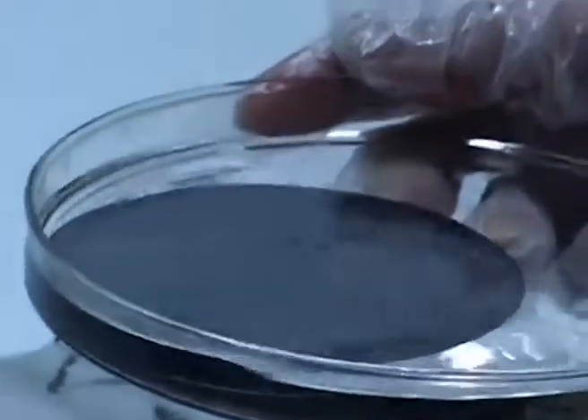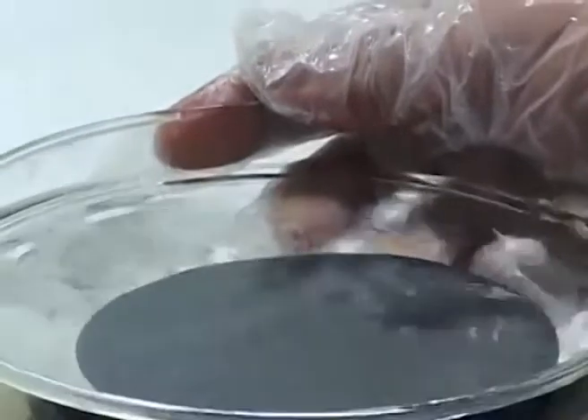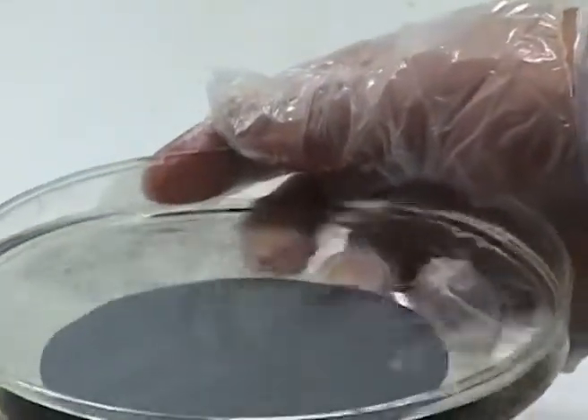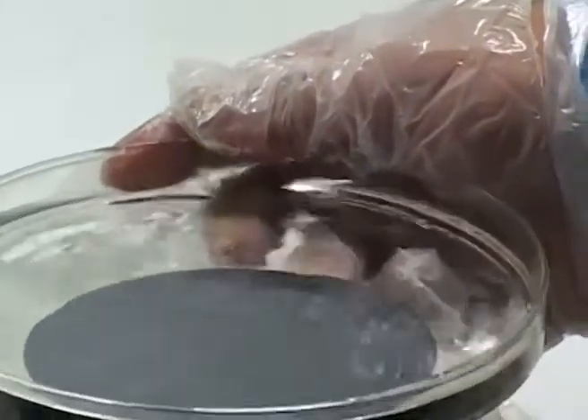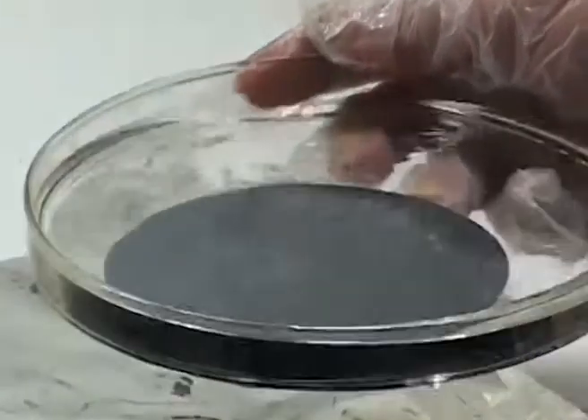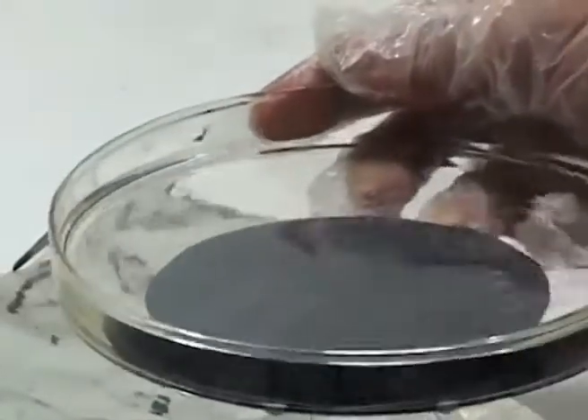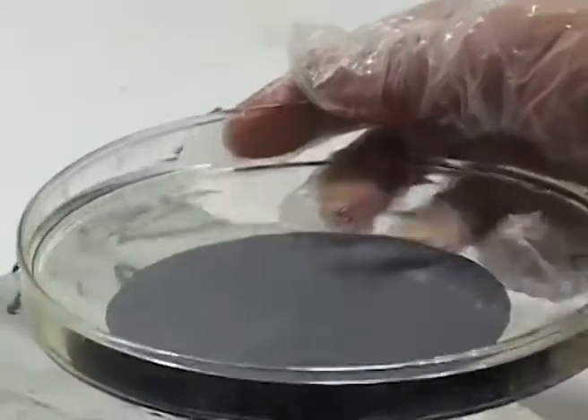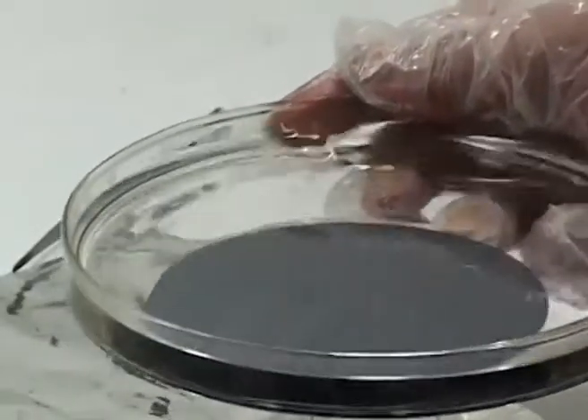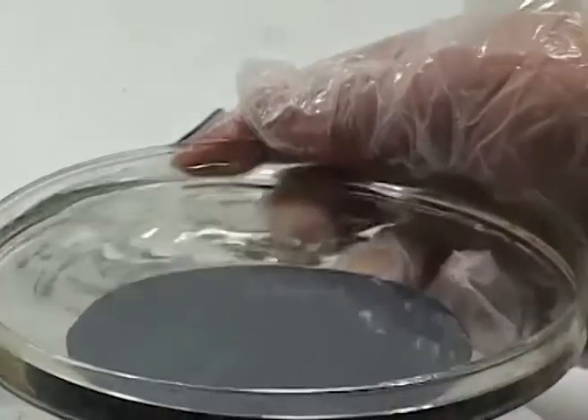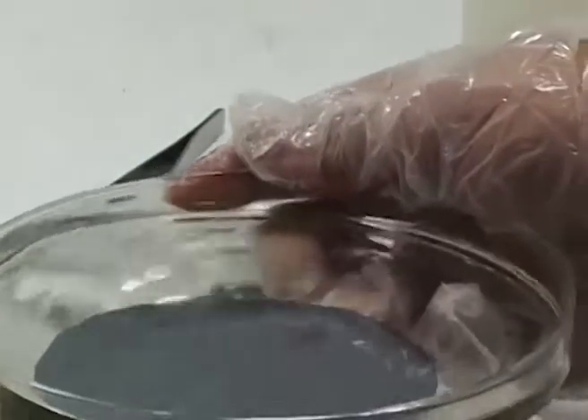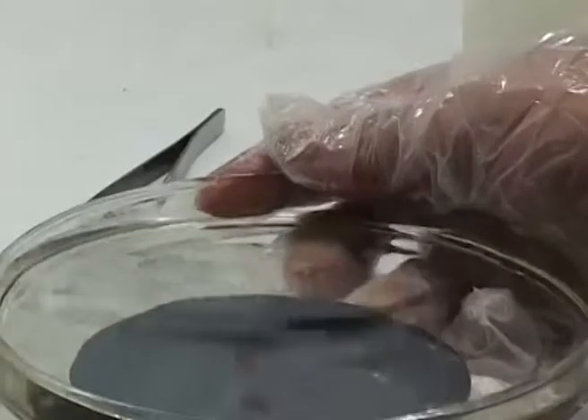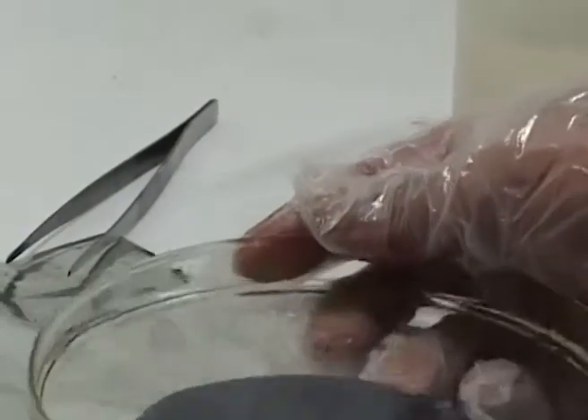So as you can see here, in this particular case, after the developing is happening, immediately after you put it into the developer, the features nicely and beautifully get generated. We need to do a proper microscopic analysis later on, but this really is the success of the process. It means that whatever you have exposed is essentially staying there, the resist is all cross-linked, and the remaining portion has been removed. And again, you have to keep circulating this and spraying isopropanol from time to time to see whether everything is remaining on the surface.